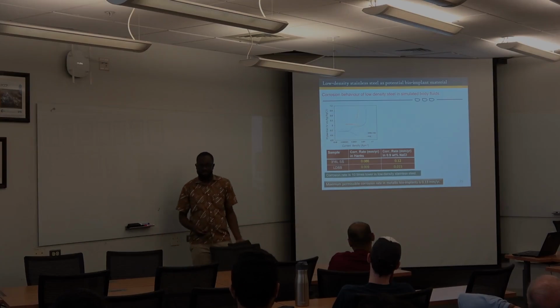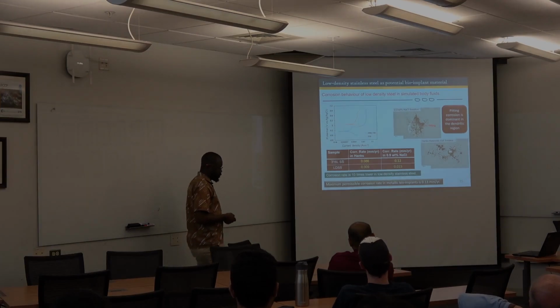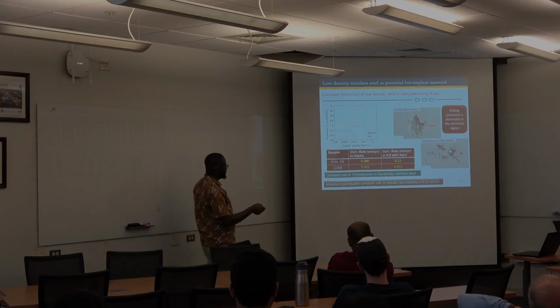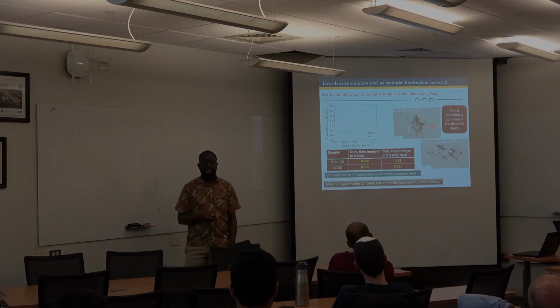And of course, if you look at these corrosion rates, they are way lower than what is acceptable for implants. And that's really why I'm much more interested in pushing this. But one thing that we found was that the alloys we first tested were in the as-cast state. You find all those dendritic structures, and they were promoting pitting. So we even thought, okay, maybe these pits are contributing significantly to the corrosion. I was like, okay, let me get rid of the pits first and see what happens.